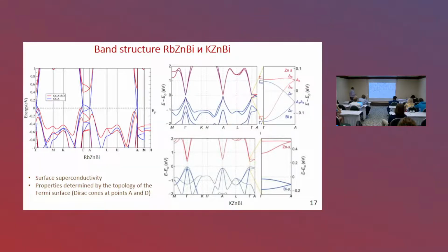Band structure calculation for rubidium zinc bismuth shows that the band structure of this compound is very close to the band structure of potassium zinc bismuth. This compound was synthesized about 2 years earlier, and in this compound surface superconductivity exists, and some Dirac point exists in this structure.